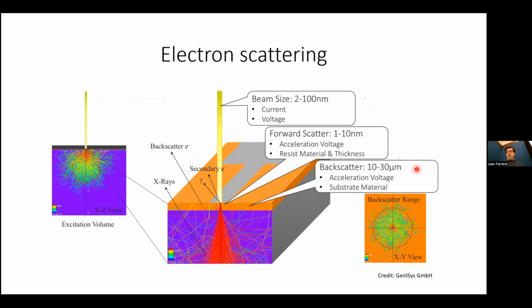And you can see the backscatter range can be as large as 30 microns. And this depends on the acceleration voltage. Forward scattering also depends on the acceleration voltage. The larger you make the acceleration voltage, or the energy of the electron that's impinging, the less forward scatter you get. But the trade-off is that your backscattering will increase. So 30 microns would be for a larger energy. And here you can see from the top how the electrons are being backscattered back into the resist, and they're creating exposure outside of the area that you want.